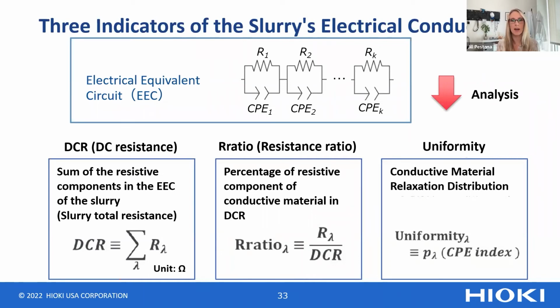So Z equals 1 divided by I omega C. Now, that's for an ideal capacitor. For this system, the capacitor isn't ideal. And this CPE index, or P sub lambda, relates to this exponential factor that ranges between 1 and 0. It's 1 for an ideal capacitor, and it never reaches 0, but as it approaches 0, you get a less ideal capacitance. So by measuring this uniformity, you're getting how close is my system to an ideal capacitor? How close are these equivalent circuits to an ideal capacitor?